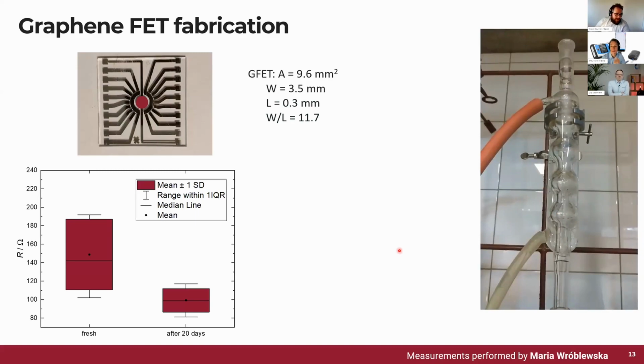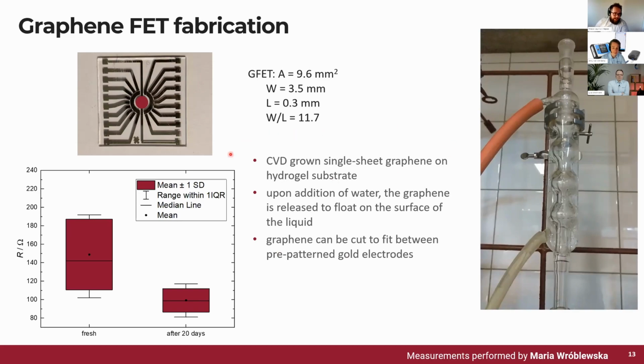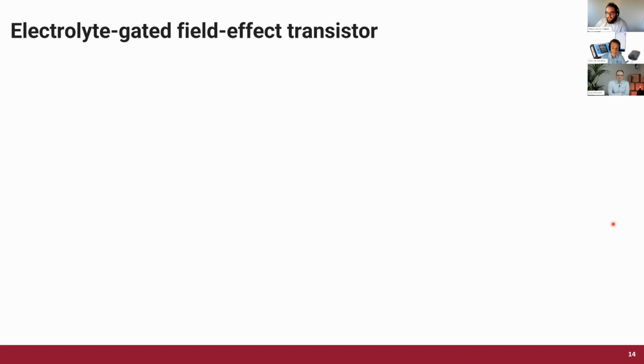freshly distilled acetone. And after getting the samples out of the Soxhlet extractor, you can see here just a 2-point measurement of conductivity with a multimeter. And you can see that the samples made in a very manual way are highly reproducible and can be used further. So in here, we use the single sheet graphene on the hydrogel substrate. Upon addition of water, it's released, then we fished it, put it into the Soxhlet extractor, got rid of the PMMA, and we're ready to measure some electrolyte-gated field effect transistors.